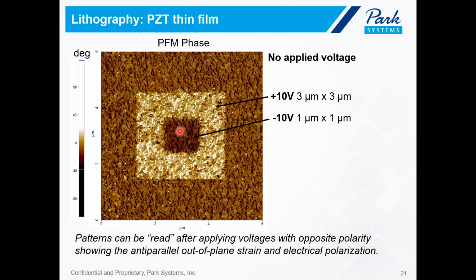And then in the center, we have the darkest region, that is the 1 micron by 1 micron scan with negative 10 volt applied DC bias to the tip. And then the region outside is our reference region, which has not been influenced by external applied tip bias and remains as randomly oriented domains. So patterns can be read after applying voltages with opposite polarity, showing the anti-parallel out-of-plane strain and electrical polarization.